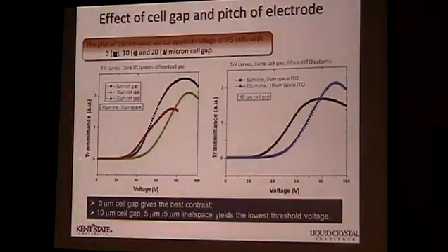Okay, so you'd like to compare those. The first one is the cell gap effect, the 5, 10, and 20. In those cases, when you have a thicker cell gap and apply a high field, you do not switch fully on, right? You have to use a higher voltage. But you know what? The materials that you have may not be so clean. What does that mean? When you try to drive it, you also use about a kilohertz, but this material has some ion effects causing some dielectric heating. So in some cases, if you apply a high voltage, it may cause some kind of dielectric heating. So what does that do to your blue phase?